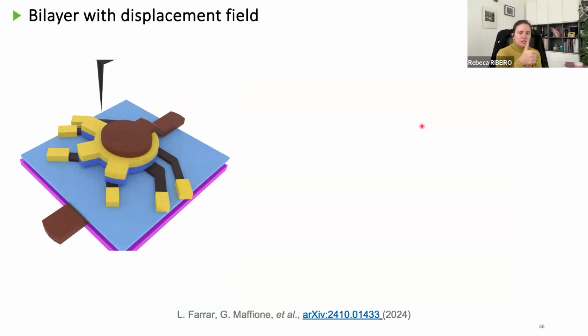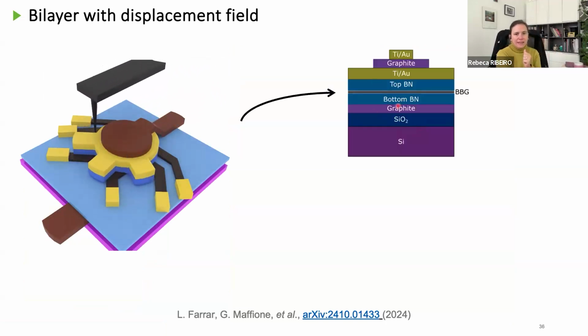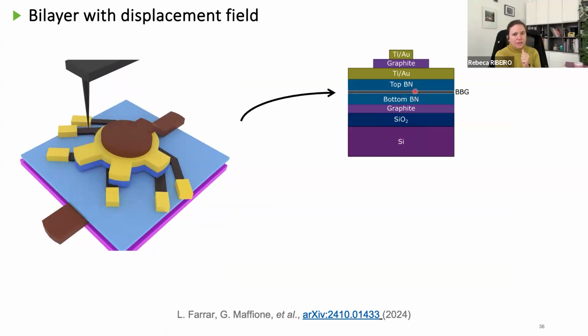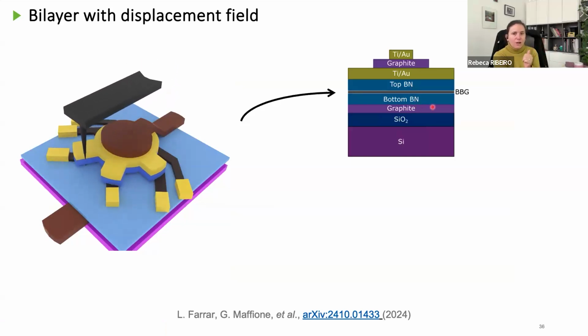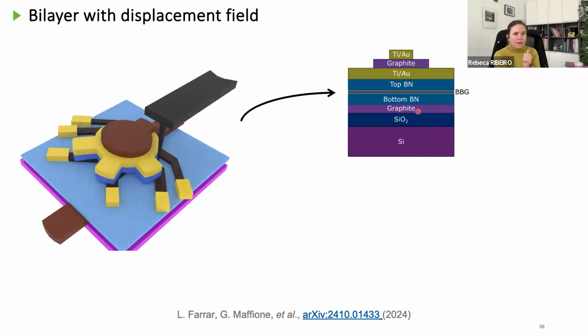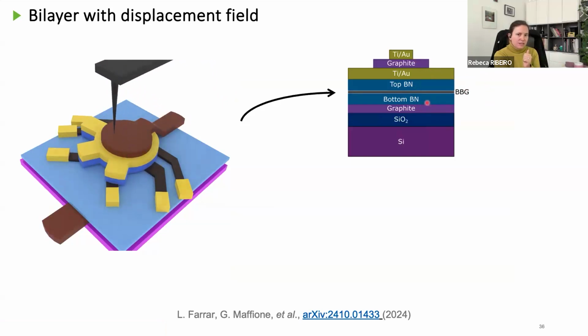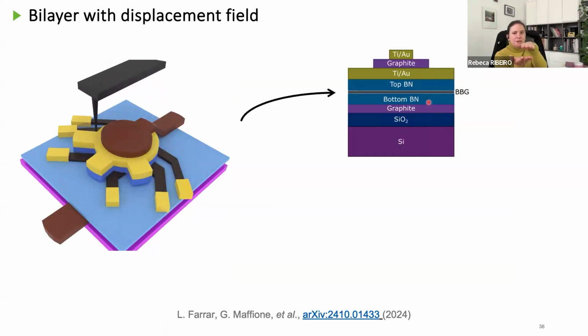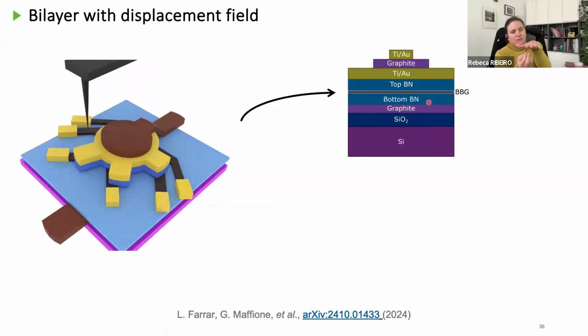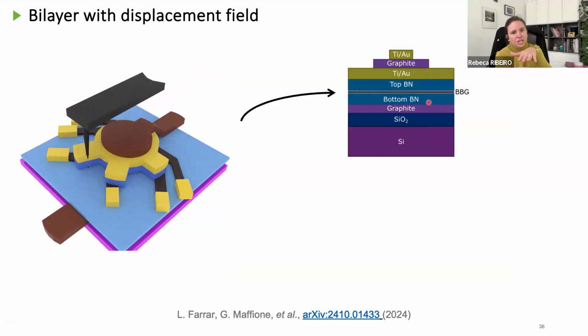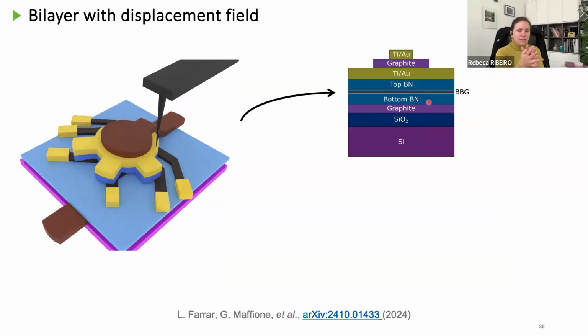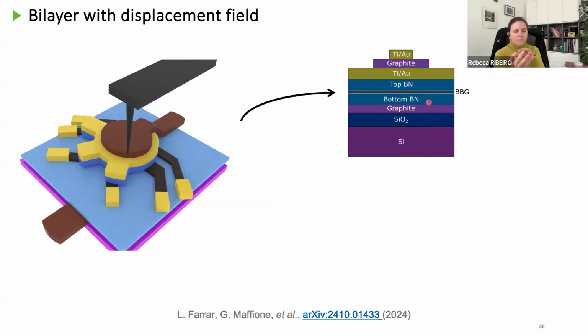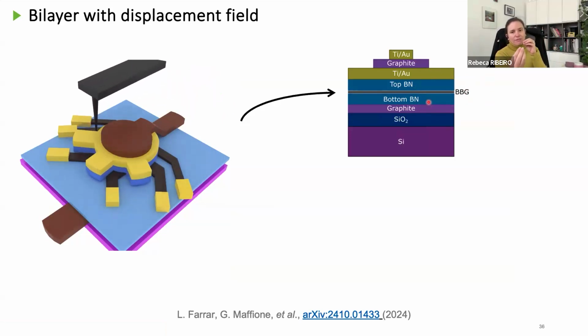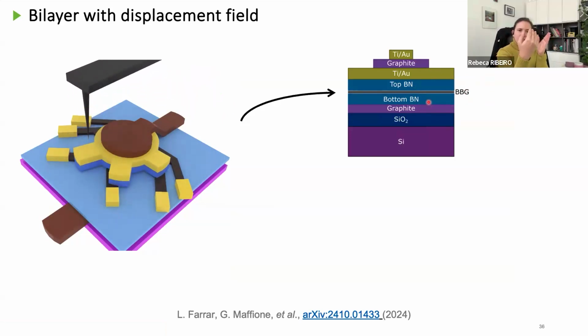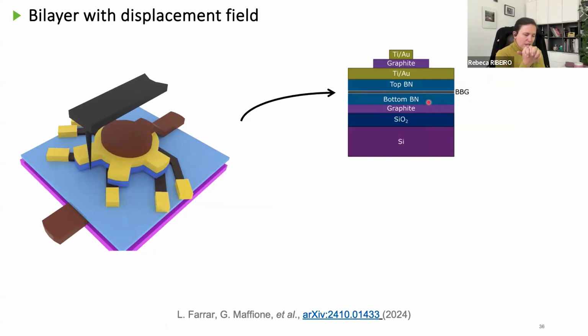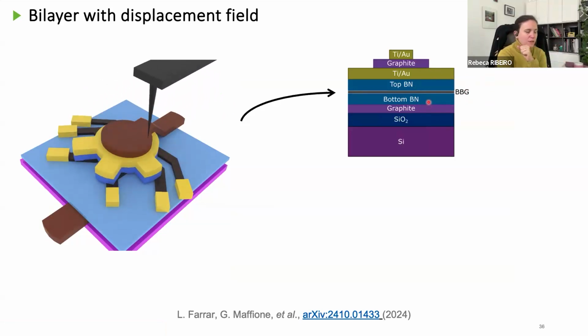So not just the regular gating effect that we were using before, but now we are able to apply two different gates to the system in order to keep the carrier concentration constant, but change what we call the displacement field. The displacement field will make the wave function of graphene localized either in the bottom or in the top layer, depending on the sign of this displacement field.